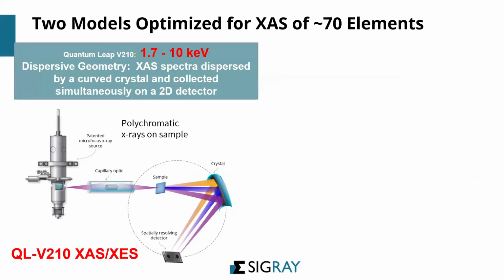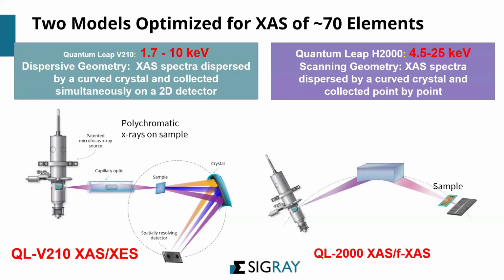So to address the need of the XAS community, Sigray came out with two models, or two products. One is a vacuum based system that can run from 1.7 keV to 10 keV, that has this particular geometry where we can now study materials all the way perhaps down to silicon. Next, this is the workhorse, the Quantum Leap H2000, which has energy levels from 4.5 to 25 keV with a scanning geometry and a very low Bragg angle.